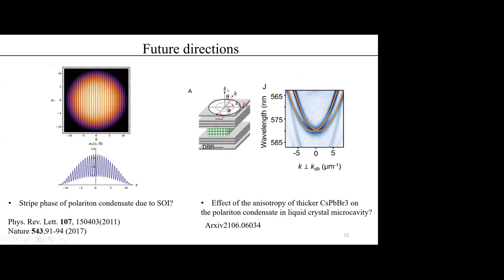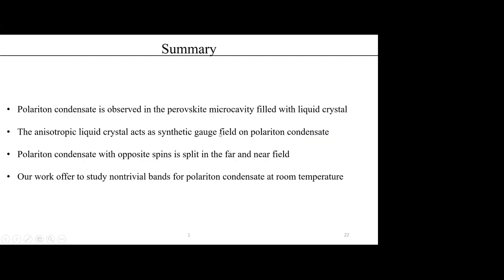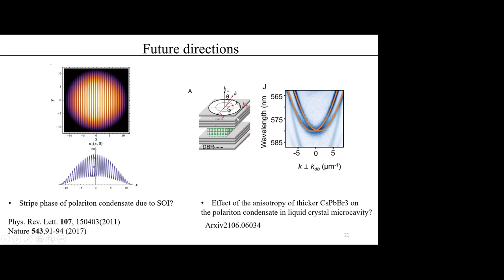Another direction is the anisotropy of the perovskite, which we do not observe in the present experiments. It looks like when the thickness of the perovskite microplate is large enough, like several micrometers, the Rashba effect can be observed in a single microcavity without liquid crystal molecules. So if we can fabricate a thicker perovskite microplate, it is interesting to study how this kind of Rashba effect affects the polariton modes just due to the anisotropy of the perovskite microplate itself.